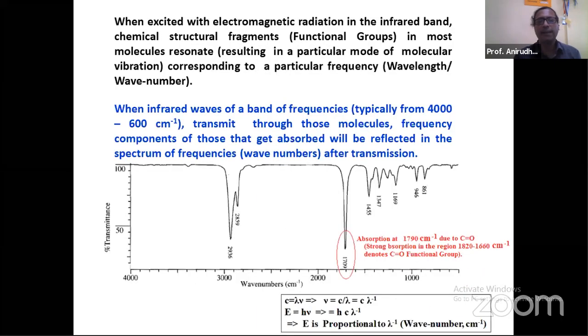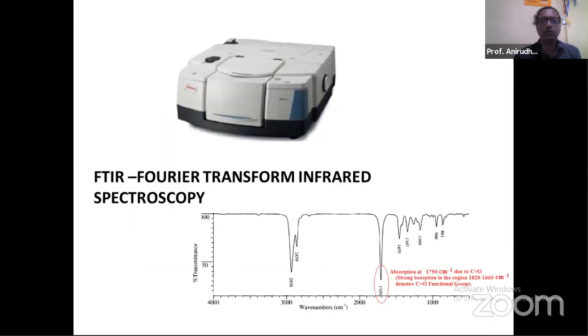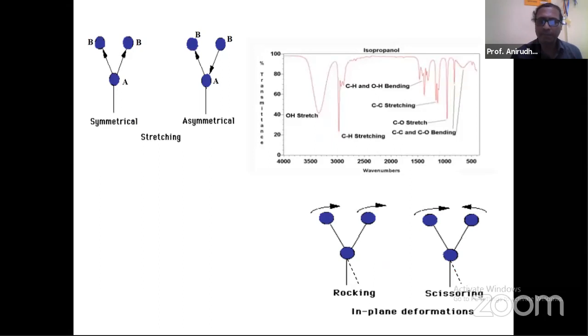The equipment is like this. You have to load your sample into this particular machine, your film, your piece from your pin-on disc machine. Say you have cut a portion from your disc, made it a thin slice, put it into this machine, and subject it to infrared rays using what is called the grazing angle IR method. That means it is not like a liquid IR system where there will be a transmission through the sample, but it will graze your surface, and then the rays after grazing your surface would reach the detector, showing those signs of absorption which have happened. I'm not going into the details of this because there is not much time left.